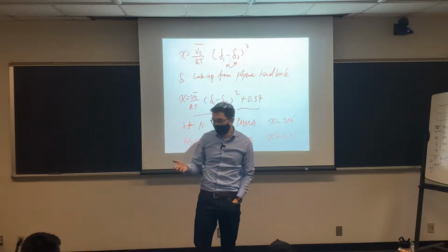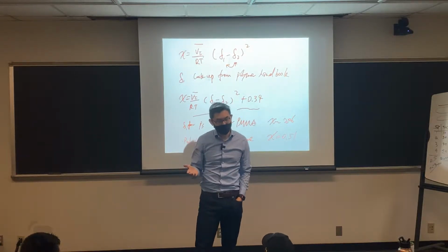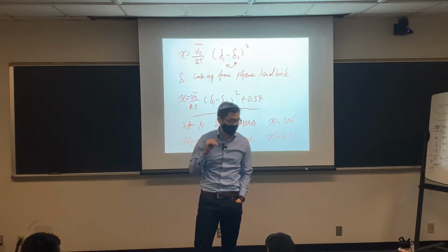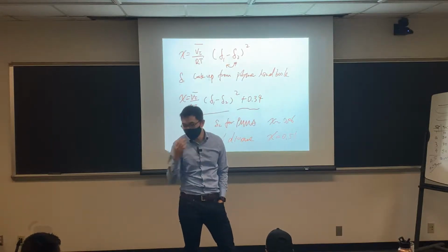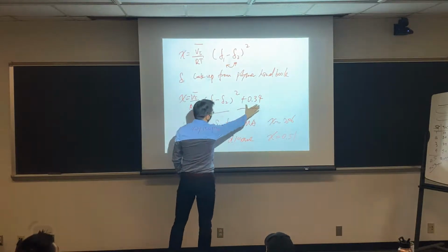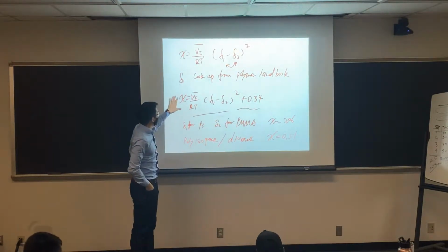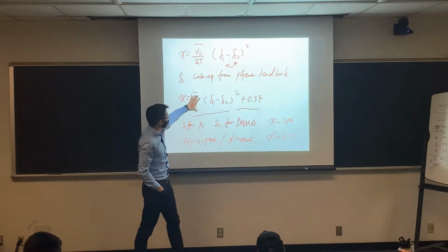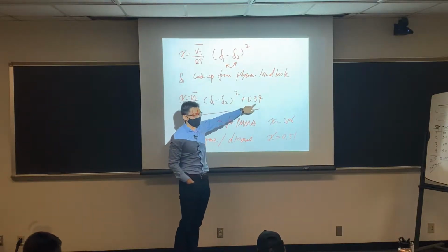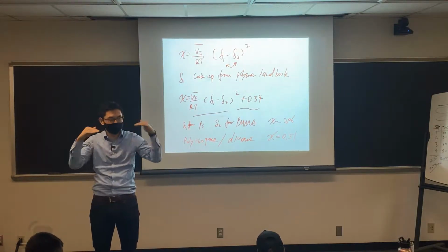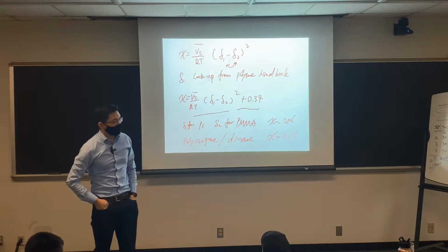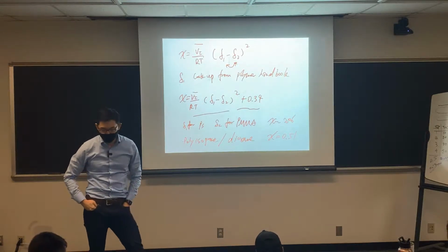The experience tells users of this approach that we're typically offset. We underestimate this value. So in real practice of this approach, we apply a constant at the end. So chi will be equal to what we discussed before, plus a 0.34 value. As you can see, you raise the baseline, which tends to raise the chi value.